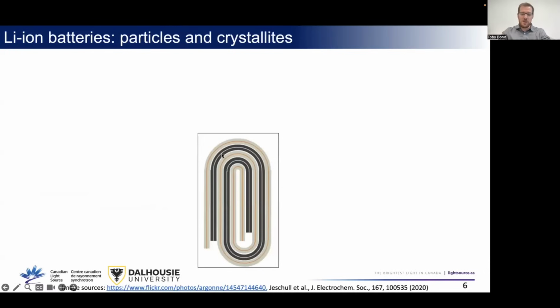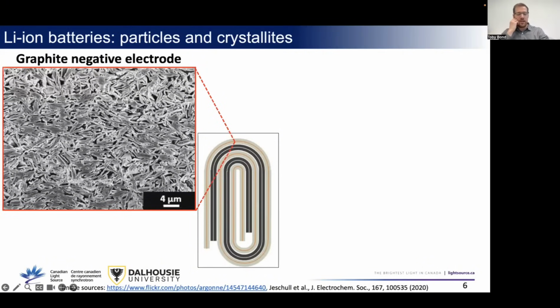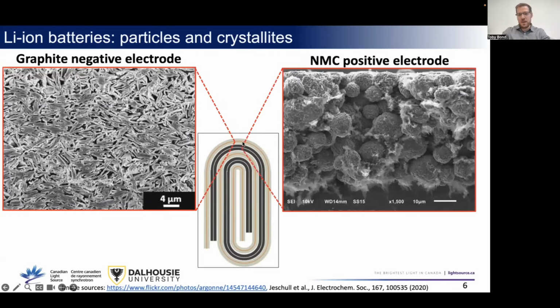So if we zoom in on one of these layers, this is what the microscopic structure of a graphite negative electrode looks like. It's these flake-like particles, and they're pressed into a thin layer on a copper foil. And the positive electrode, NMC and NCA, looks something like this. There are these little balls that we call secondary particles. These balls are held together with a polymer binder that has a conductive additive so that you can conduct electricity between the balls and out to the terminal.